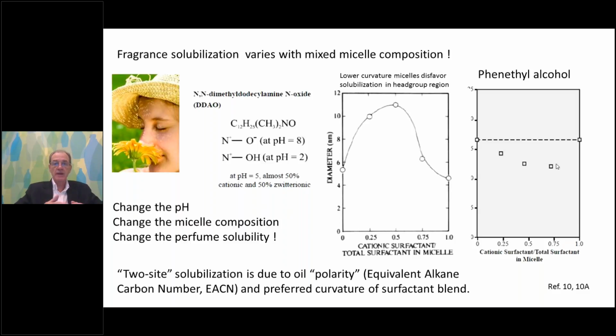Well, the way to think about this is that the opposite would apply as well. If we had a fragrance oil that would solubilize primarily on the interior of the micelles in the hydrophobic region away from the head groups, then it can actually change the net curvature of the micelles and shorten or eliminate the rod-like micelles, pushing them back towards spheres. So this idea of two-site solubilization for a given oil of some polarity, or really more properly, its equivalent alkane carbon number, or EACN, is a very real phenomenon that affects, in the end, the net curvature of the system, and in the end affects how much fragrance I can deliver as I change my mixed micelle composition.